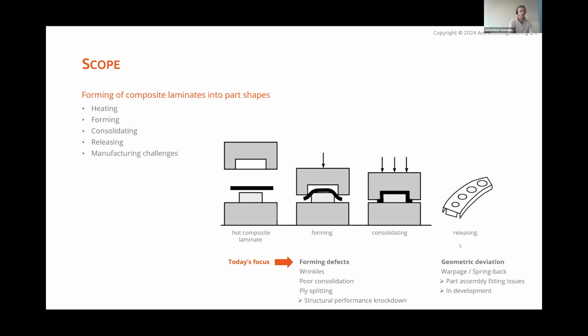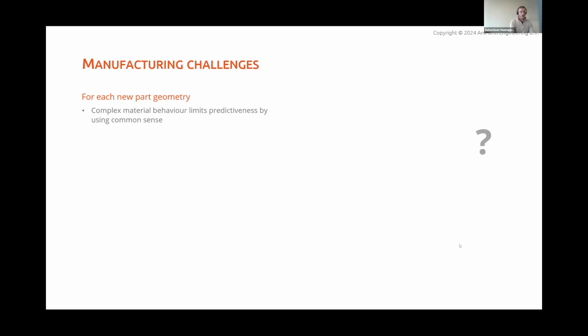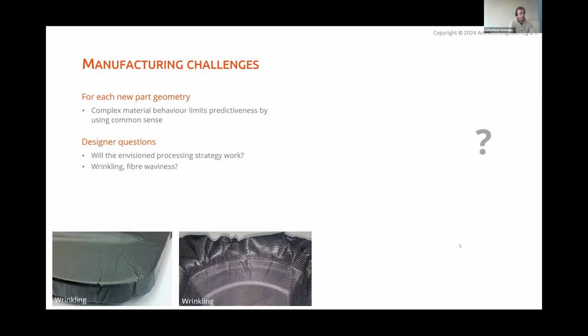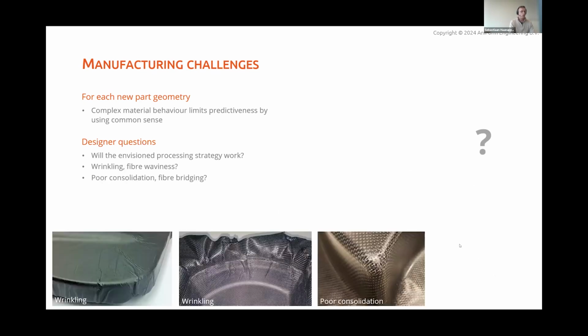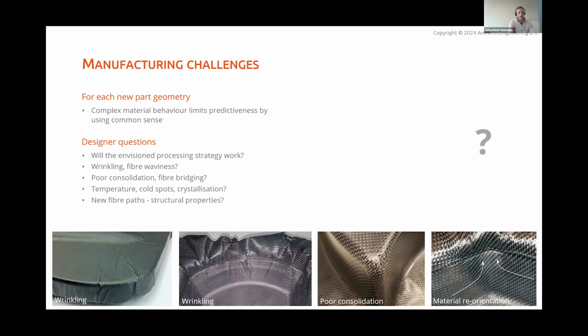And yes, it may be clear that there are quite some manufacturing challenges. So what about these? Well, what we see is really for each new part geometry, the complex material behavior of these composites in their molten stage really limits just using predictiveness by using common sense. And we see a lot of designer questions like, well, I have a process strategy in mind, but will it actually work? Will I have wrinkling or fiber waviness, and where does it occur? What about this poor consolidation? Caused a lot by fiber bridging, when fibers span corners, for example. What about my temperature? What about cold spots and crystallization? When I form a part, I get new fiber directions. We get material reorientation. What will it do with the structural properties?